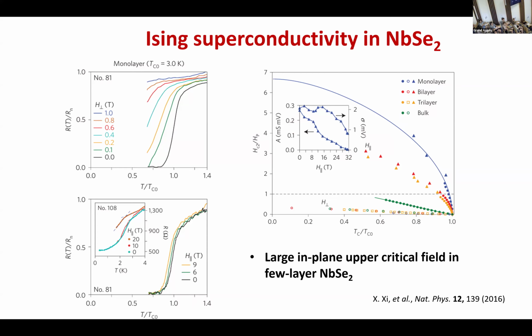But I think it's becoming more and more consistent because when people change the material, for example, changing niobium diselenide to tungsten disulfide, which has heavier atoms, then you see this effect becomes stronger because the spin orbit coupling is stronger. So the Zeeman-like splitting becomes stronger. So in that sense, it's kind of consistent. Also, people observe that when you go to bilayer or trilayer, this effect becomes weaker. The reason is that when you go to these thicker layers, this inversion symmetry breaking effect becomes weaker. Each layer is still inversion symmetry broken, but the total system actually preserves the inversion symmetry.